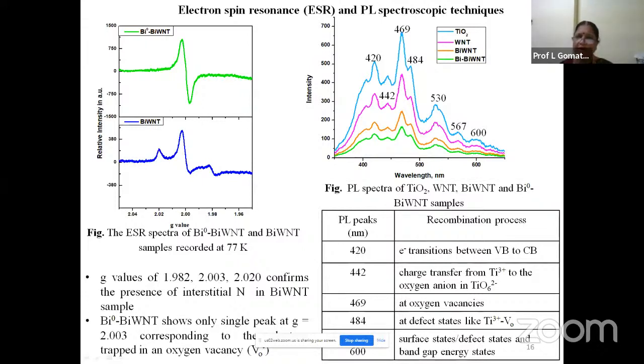At 420, it is the electronic transition between the valence band and the conduction band. At 442, it is the charge transfer from Ti3+ to oxygen anion in TiO6 octahedra. At 469, the recombination is occurring at oxygen vacancies. At 484, it is a recombination in the defect states like Ti3+ and VO. And at 600, it is surface states or defect states or band gap energy states where the recombination can occur.